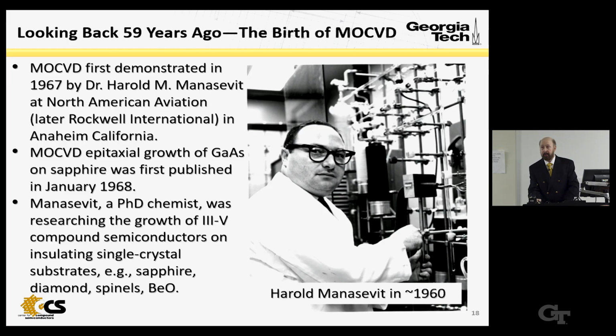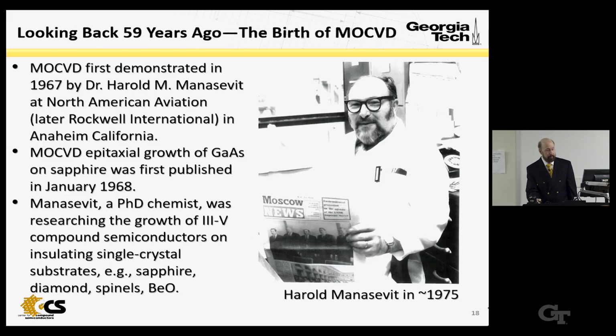Where he was growing gallium arsenide on sapphire, beryllium oxide, spinel, various insulating crystals, and it was first published in January of '68. Manasevit was a PhD chemist, inorganic chemist, and he was looking at heteroepitaxy on insulating oxide substrates for, I won't go into the details, but he had a really good reason for wanting to grow on insulating oxide substrates. This was the only technology that could do that.